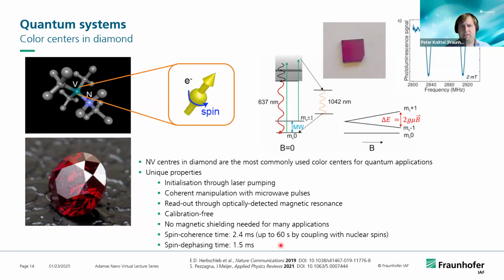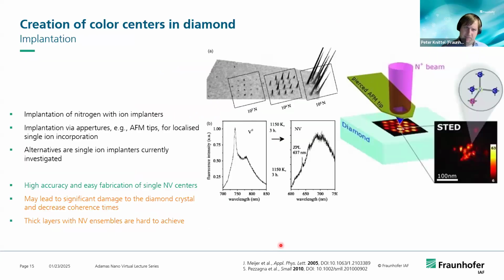How do we get these NV centers into diamond? There is a straightforward approach that is used in many groups, especially if they want to create single centers. Here you can basically implant the nitrogen atom. With that, you already generate vacancies in the crystal lattice. You make these vacancies mobile by a thermal treatment afterwards, and with that, you end up having an NV center formed. So this is basically an easy approach that allows you to generate single NV centers.